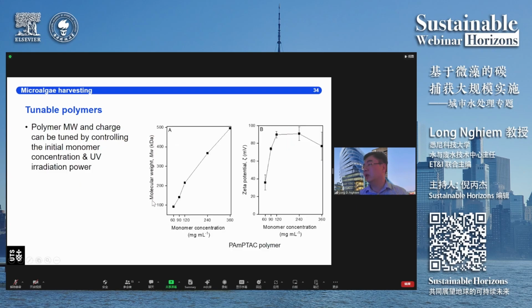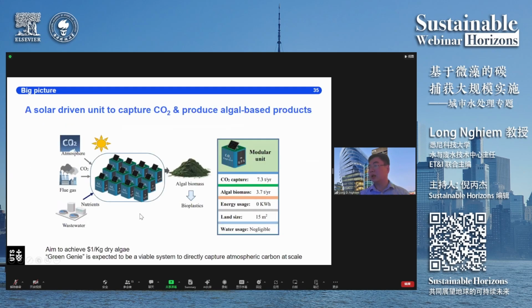And we have recently obtained some proof of concept data to show that by changing the monomer concentration, we can change the polymer molecular weight at the end. And likewise, when we change the monomer concentration, we can also change the zeta potential or the surface charge or the surface density of the polymer to some extent. We have also got some preliminary data to show that the same thing can be done by changing the UV strength. So I just want to quickly put everything together.